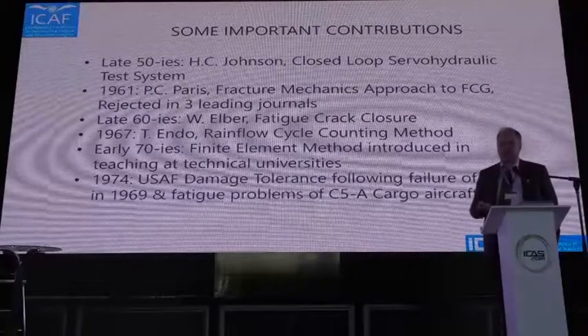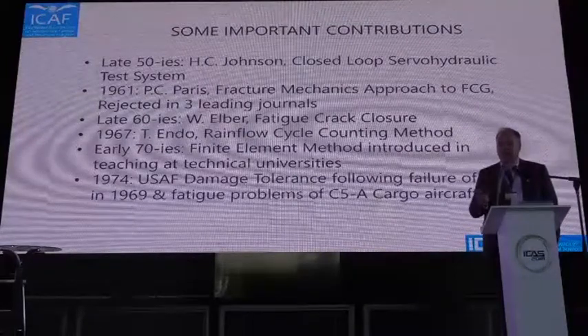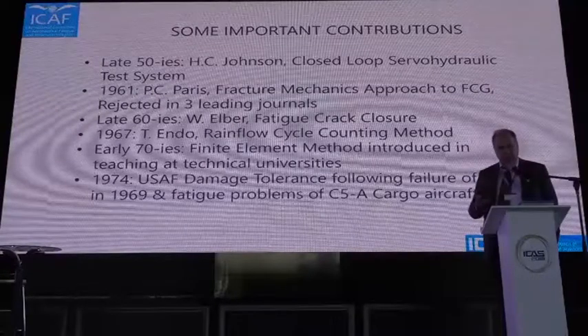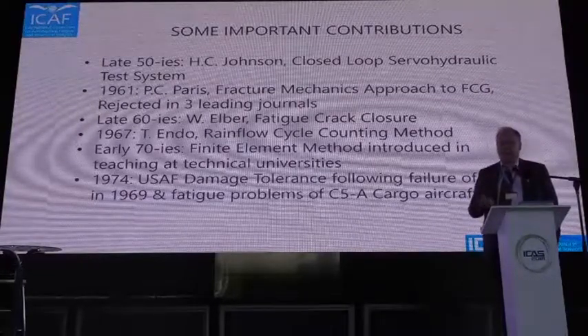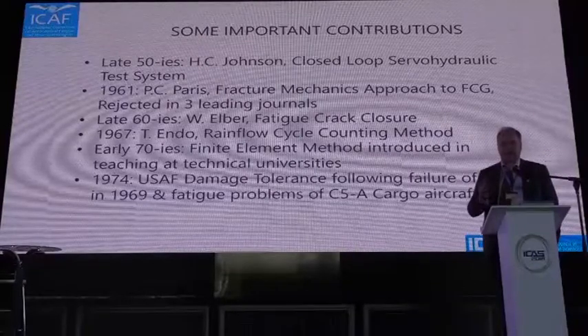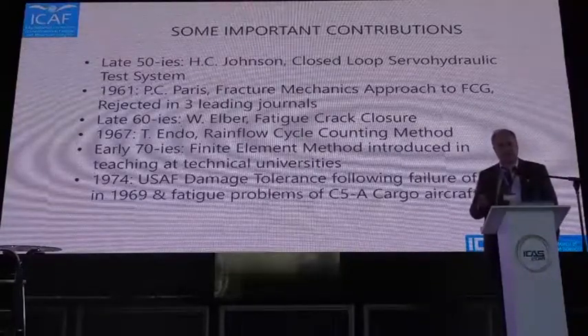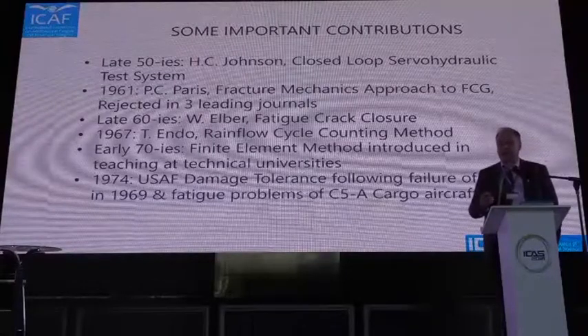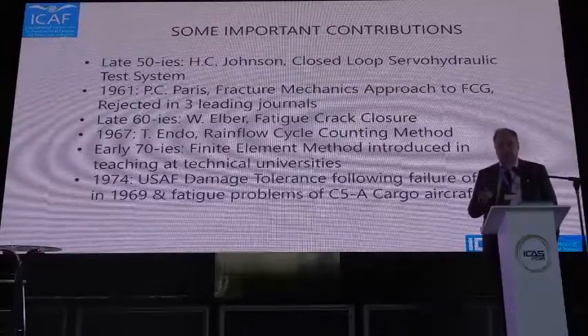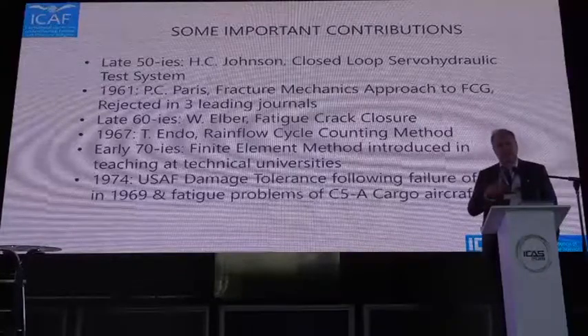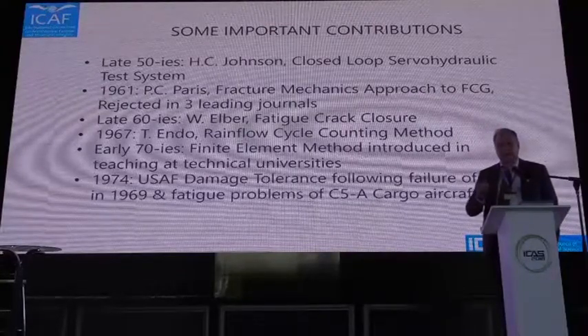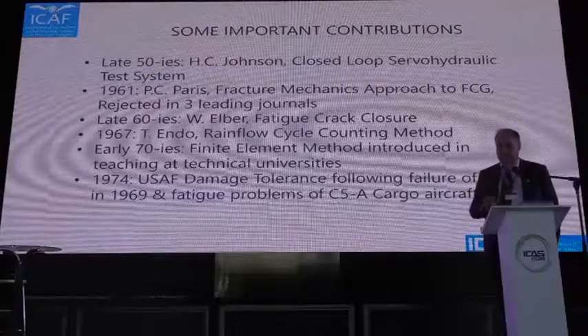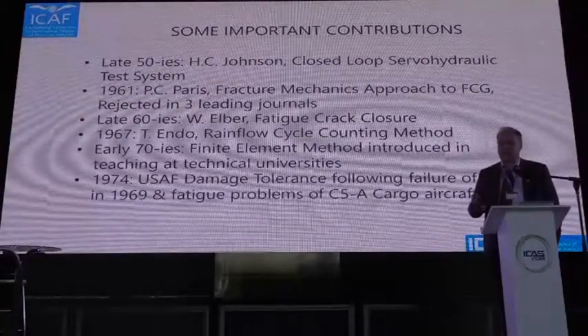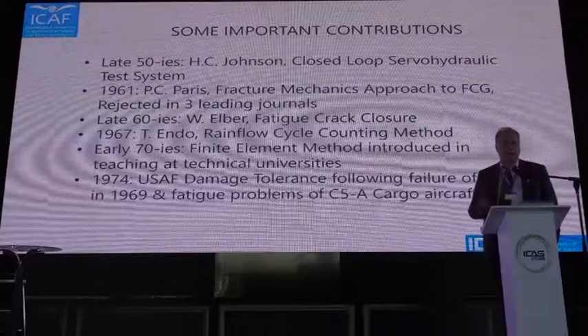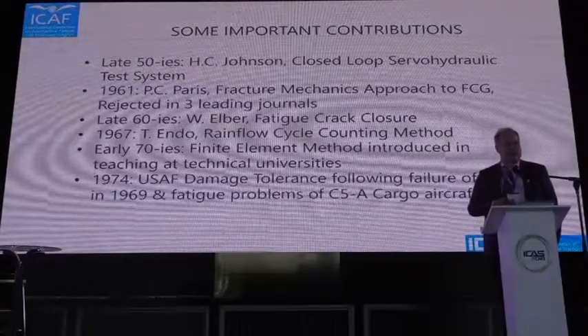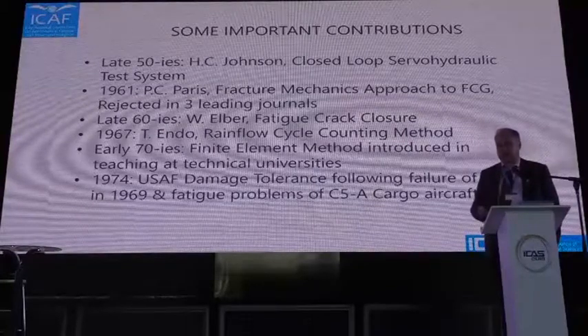However, now it's very well understood that as long as we have what is called small-scale yielding, which we normally do at the lifetimes we operate, the stress field at the crack tip is characterized by the first term in the series expansion. This is called the stress intensity factor, and that has an inverse square root singularity. So the stress goes to infinity at the crack tip, but of course yielding will stop the stress from becoming infinite. And the good thing in this is that it's not dependent on planar geometry, so we can transfer data from test specimens in the lab to the structural calculations we do for real aircraft.